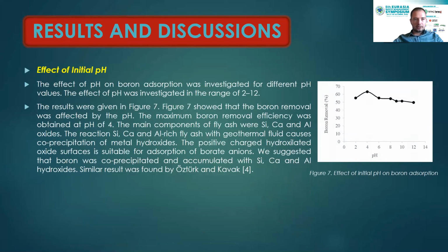Effect of initial pH. The effect of pH on boron adsorption was investigated for different pH values. The effect of pH was investigated in the range of 2 to 12. The results were given in figure 7. That figure showed that the boron removal was affected by the pH. The maximum boron removal efficiency was obtained at pH of 4.